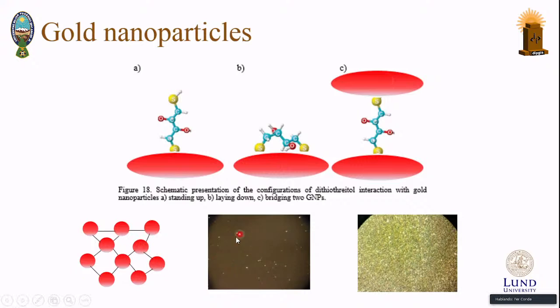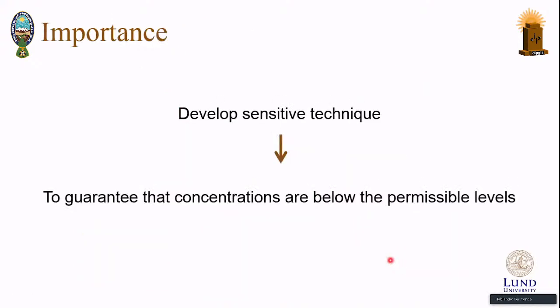So here we can see the gold electrode without the net formation of gold nanoparticles. And here we can see the net formation of the gold nanoparticles with dithiothreitol. The importance of this study is to develop a sensitive technique to guarantee that concentrations are below the permissible level, as was shown before.